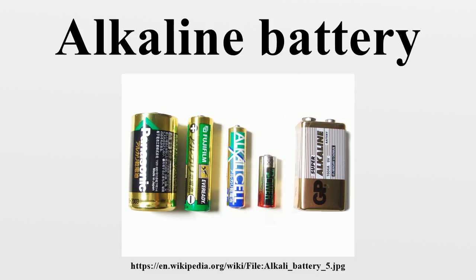The reason for leaks is that as batteries discharge, either through usage or gradual self-discharge, the chemistry of the cells changes and some hydrogen gas is generated. This outgassing increases pressure in the battery. Eventually, the excess pressure either ruptures the insulating seals at the end of the battery, or the outer metal canister, or both. In addition, as the battery ages, its steel outer canister may gradually corrode or rust, which can further